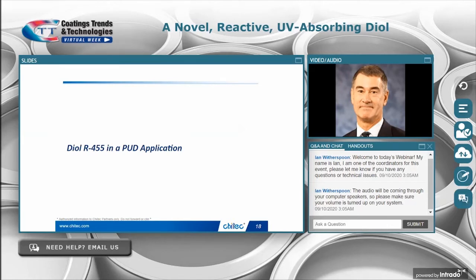A UVA like CHIGUARD 5530 has a polyethylene oxide side chain, which does make it reasonable to formulate into a waterborne coating. But this UVA is somewhat less efficient due to lower active chromophore content, and it does not have long-term field retention due to worse photopermanence. So it's not a great way to go.